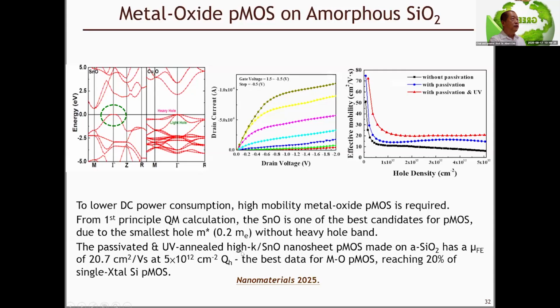With the passivation and the UV anneal, the high-K tin monoxide nanosheet PFET made on amorphous silicon dioxide has a mobility as high as 20.7 at 5 times 10 to the power of 12 hole density. The best data for metal oxide PFET, reaching 20% of a single crystal silicon PMOS. We reported this result in Nanomaterials this year. Right now, we can even reach almost double the mobility, about 50% of a single crystal silicon.